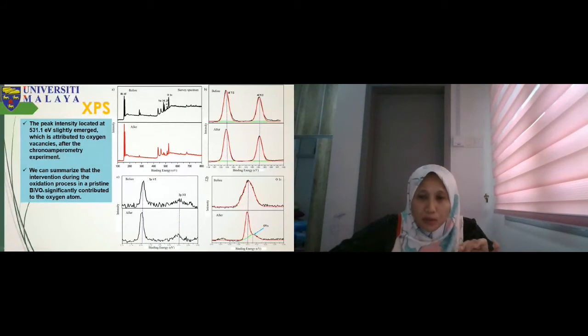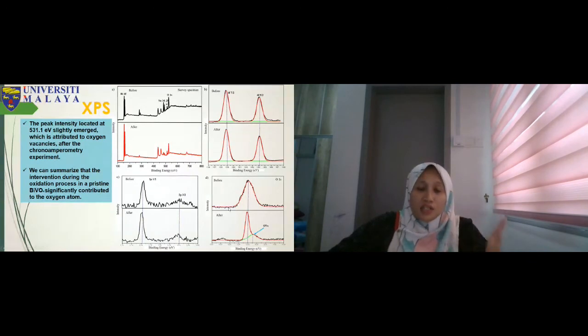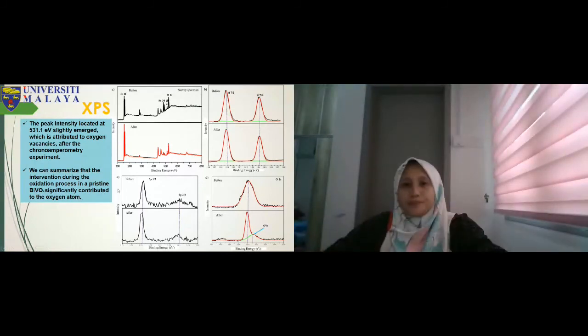Based on this finding, it can be observed they are different here in the oxygen, because the peak intensity located at 531.1 eV slightly emerged, which is attributed to the oxygen vacancy after the chronoamperometry experiment. We can prove that during the redox reaction, the oxidation process can occur in our sample. And we can summarize that the oxidation process in a pristine sample can contribute to the oxygen atom.